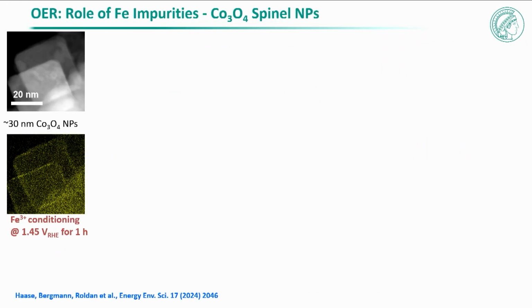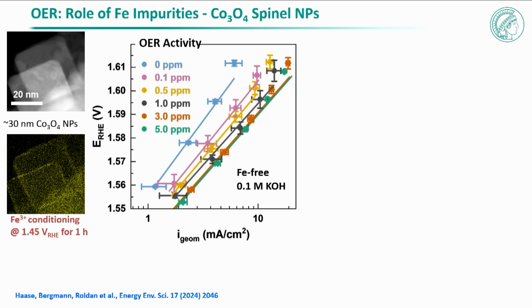So when you are talking to the industry and you give them this wonderful data under ultra pure conditions, experimental data, they will tell you, yeah, but our electrolyte is not ultra pure. And what is the most common impurity that you have in water is iron. So we try to understand what does iron do to this catalyst during water splitting. So we make a catalyst, in this case, these were cobalt oxide particles, and then we put it in an electrolyte that contains iron. And just a very small amount of impurities. And you see that you start making these structures, so you get iron incorporated into your material.